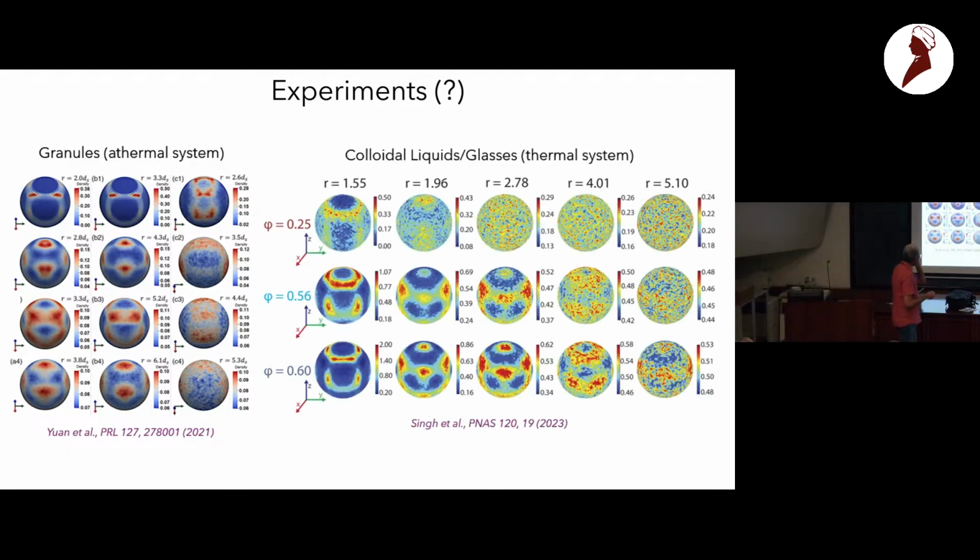We did colloid experiments. So this was athermal, so we went to colloids. What I'm showing you here is the density at 3 different packing fractions. Once again, you see this sort of beautiful order, and the composition of the colloid mixture was identical to the Kob-Andersen mixture. So it was an 80-20, roughly the same particle size ratio. And you once again see this sort of order emerge all the way to distances exceeding 5 sigma.